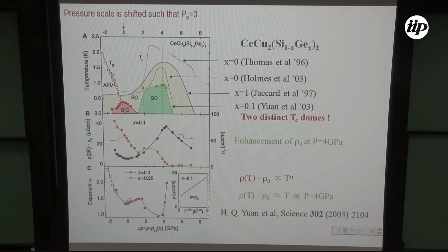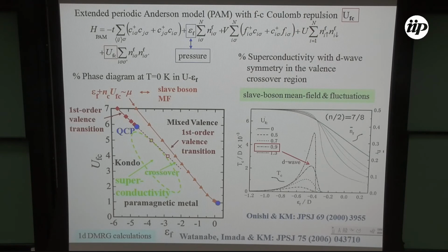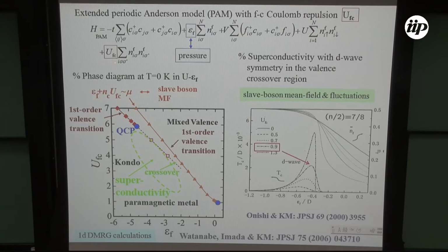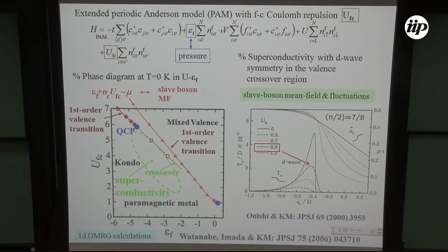Another remarkable thing is that CeCu2Si2 with 10% of silicon replaced by germanium shows two separate domes, and also shows a rapid increase of rho 0, and the exponent of resistivity shows linear. We will have some theory on the basis of the periodic Anderson model with repulsion between f and conduction electrons, U_fc.